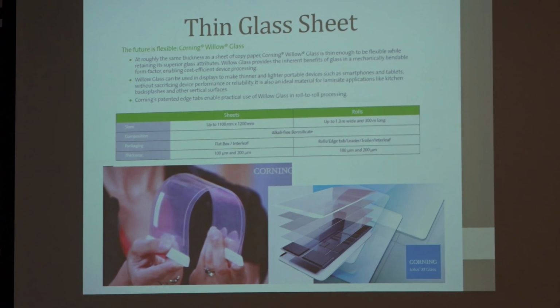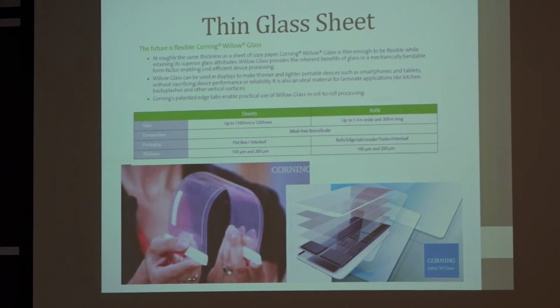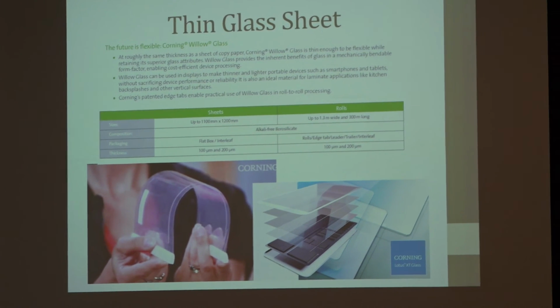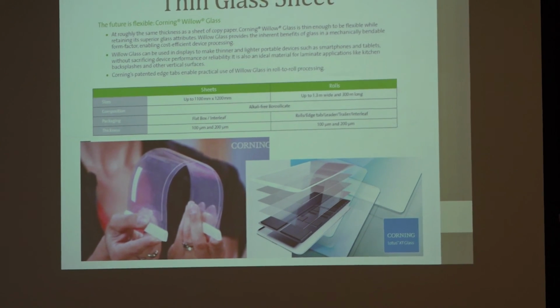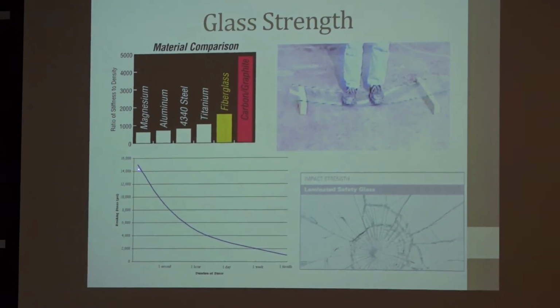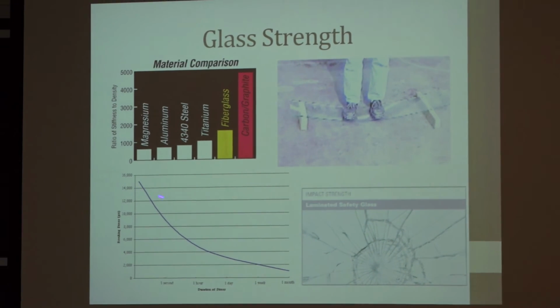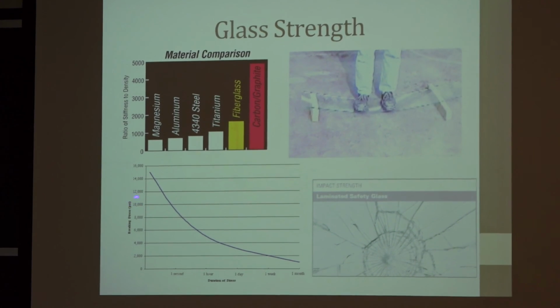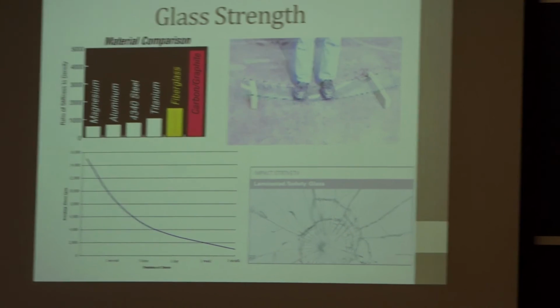Glass is significantly harder. But the problem, did you tell them about the problem of corrosion of glass? Most glass that we know of has a significant decrease in strength over time. This is duration of stress versus the bending stress. And glass starts out at 14,000, is that megapascals? I can't see it from this angle. PSI. 14,000 PSI. About as strong as aluminum, okay? Regular aluminum, not super aircraft grade.